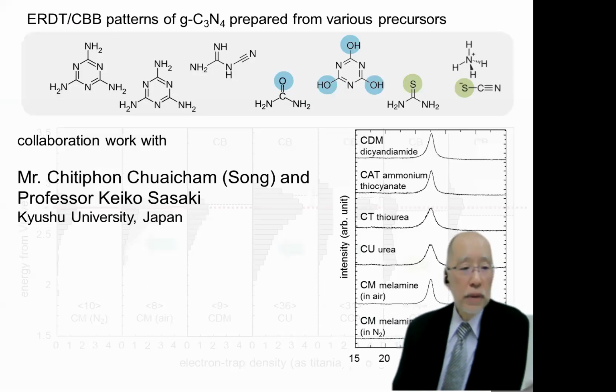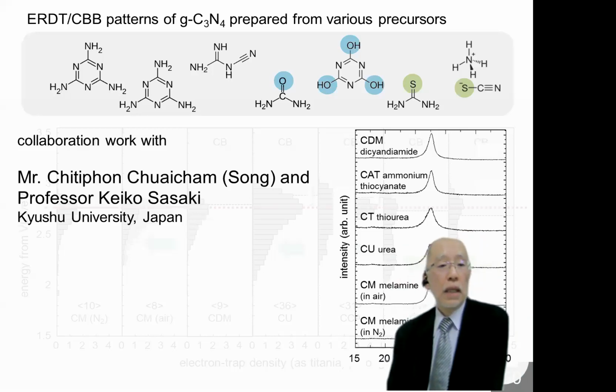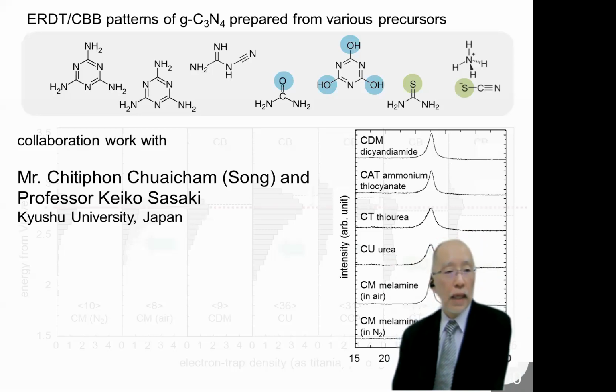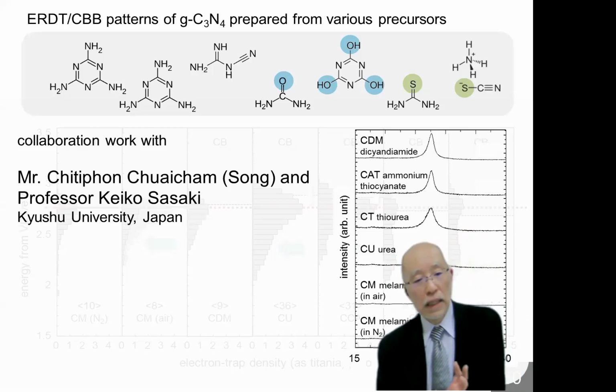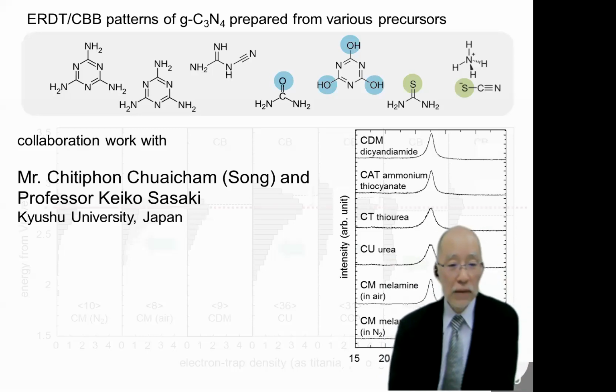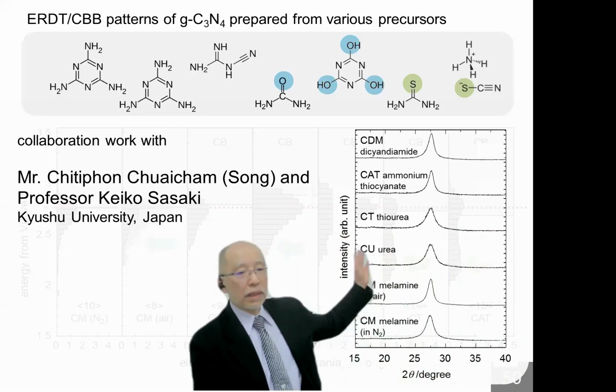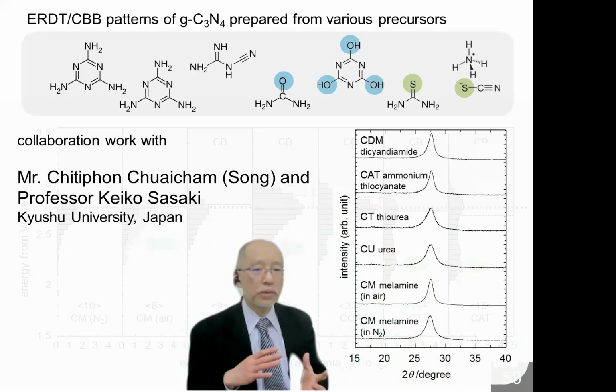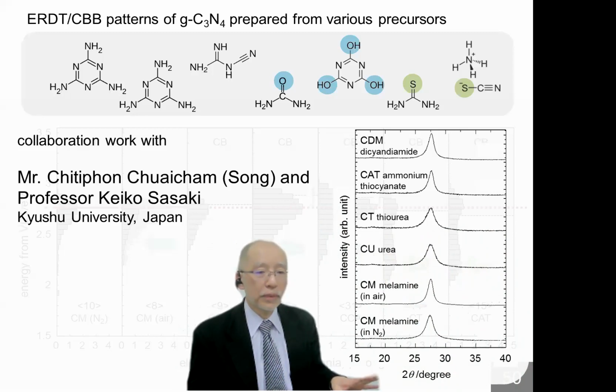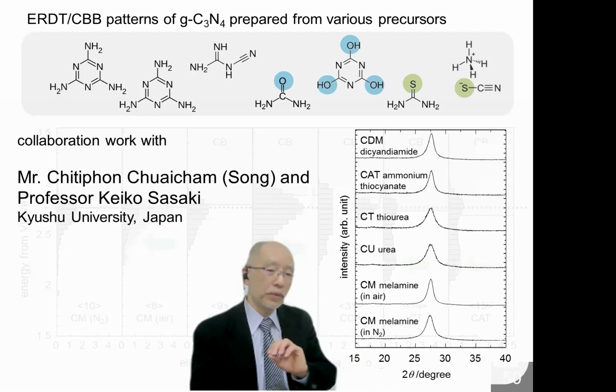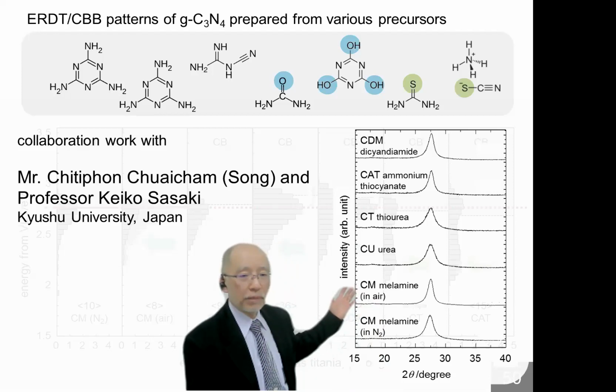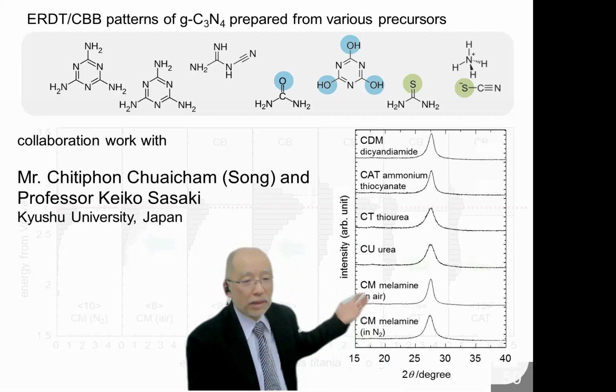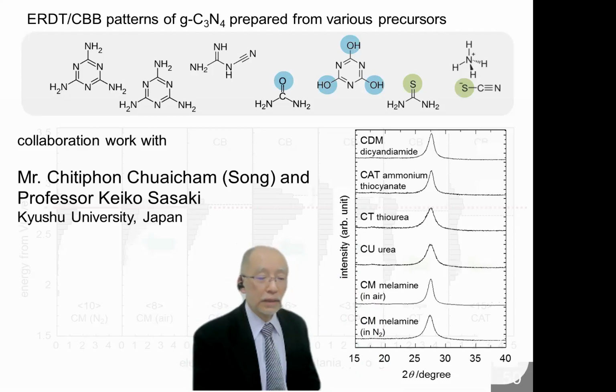And Son-san in Kyushu University, with the collaboration of Professor Sasaki Sensei, prepared the C3N4 graphitic carbon nitride that is categorized as a semiconductor, and that might be an inorganic compound. And by changing the starting material, it is possible to prepare different types of carbon nitride that are doped materials. But the XRD pattern gives almost the same patterns. And it is a bit difficult to find the difference between those samples in XRD patterns.